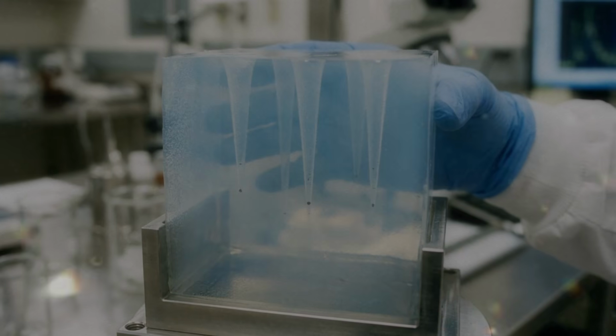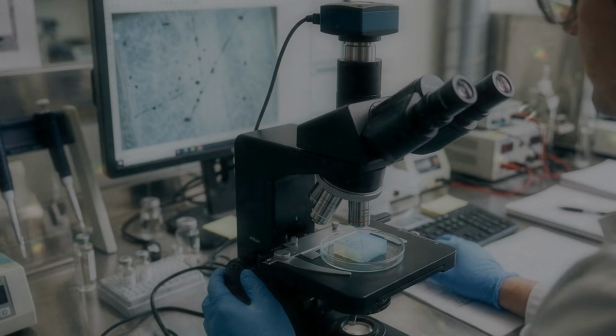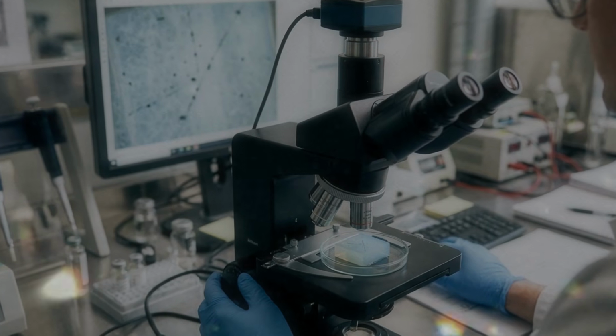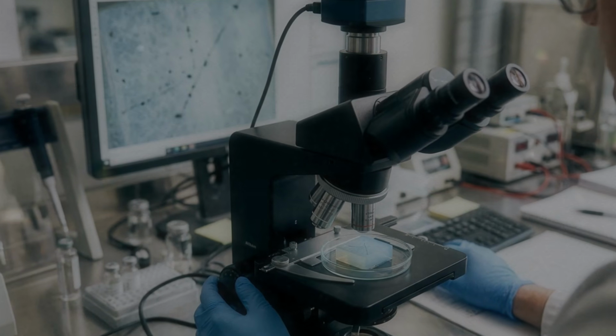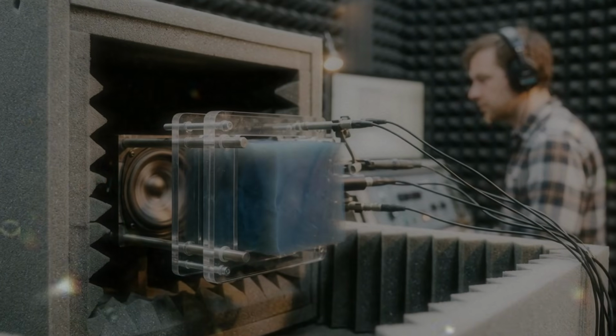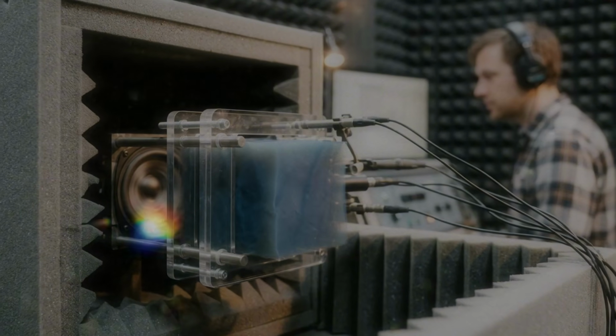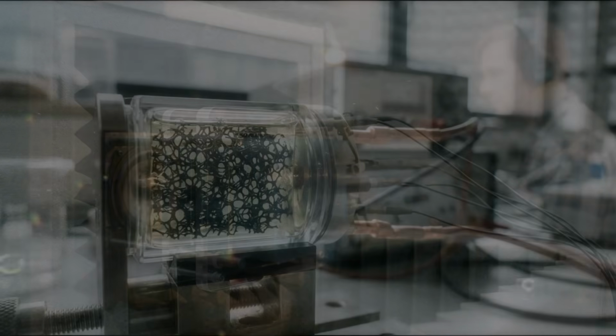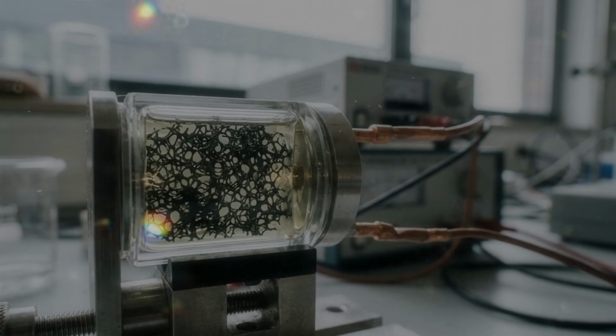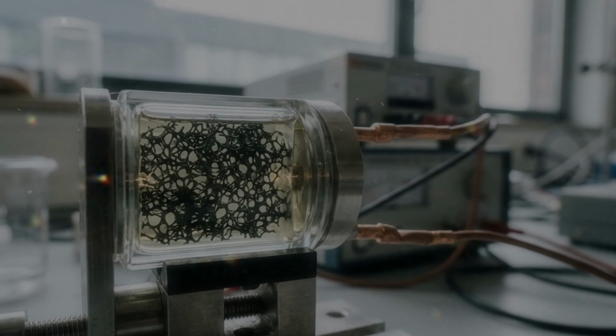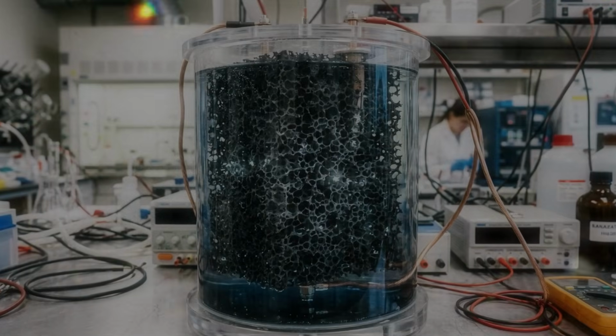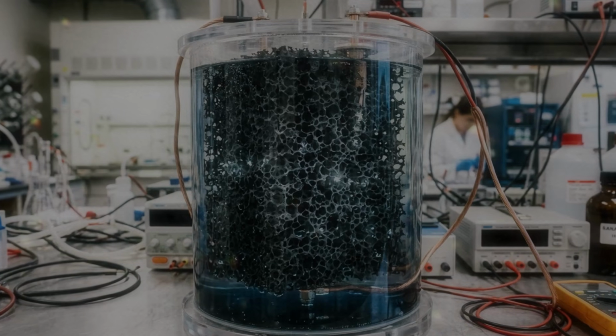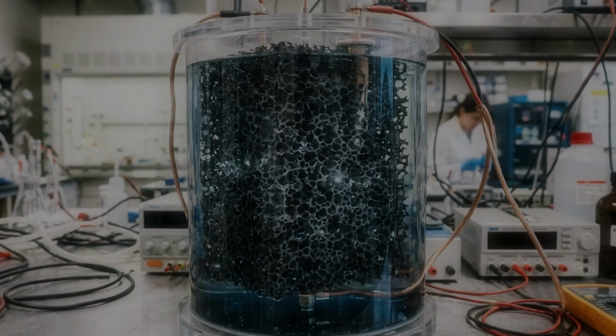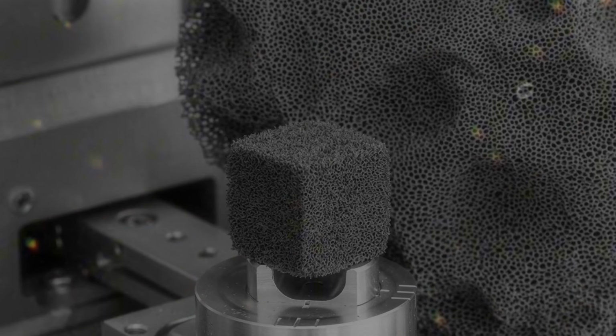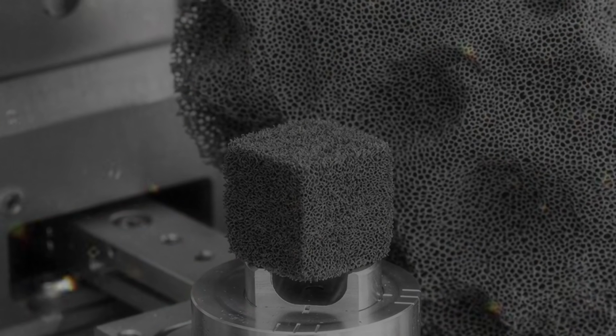The density also matters. Adding more solid material can increase strength, but it also increases weight and may change the insulating behavior. Designing an aerogel often involves balancing several properties that do not improve together. The phrase lightest material can therefore hide an important trade-off. Removing more solid matter usually lowers density, but it can also weaken the structure. At some point, the network may become too sparse to support itself. The achievement is not simply making something lighter, it is making something lighter while preserving enough connection to remain useful.